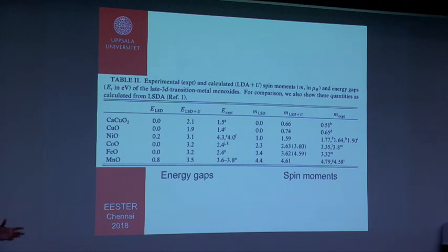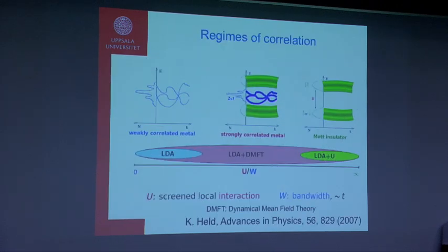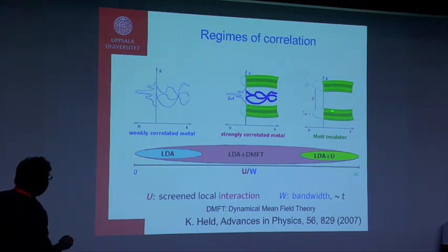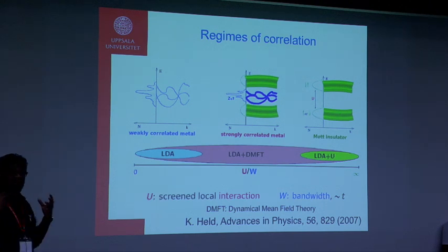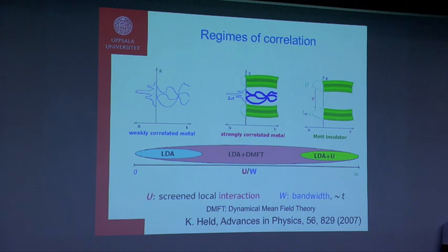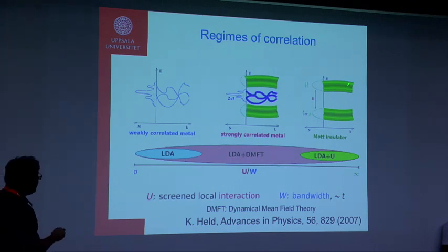So this is the mean field picture, but this is a static mean field picture, the DFT plus U technique. But we should think of going beyond this picture and do something better. So I was talking about regimes of correlation. One can look into different material systems, and you can divide the systems into different types of materials. For example, on the left hand side, I have a weakly correlated metal, normal metal. On the right hand side, I have a strong electron correlation present in Mott insulators like these oxides, where you see the lower Hubbard band and upper Hubbard band that opens up a big gap, things like that.